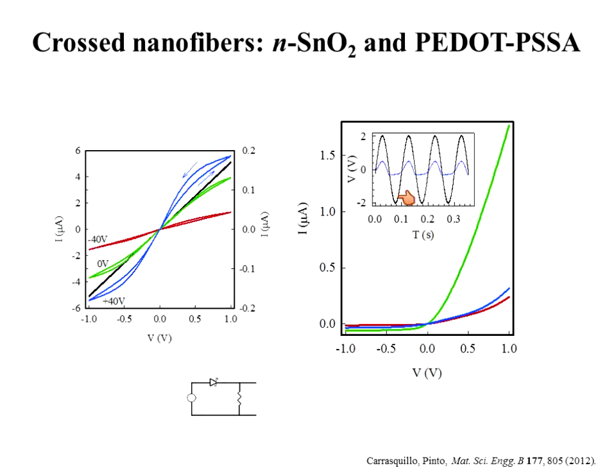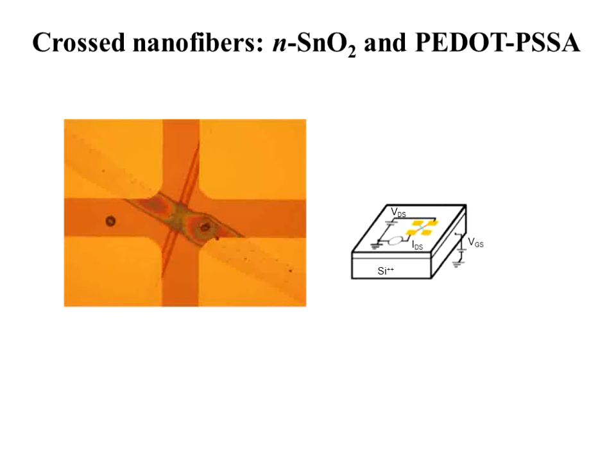But you see that the sine wave is applied at the entrance over here, and this voltage across the resistor would be this blue one. It's not a perfect half-wave rectifier, but it does show some waveform clipping. So a very simple device like this can show you waveform clipping, and showed you that one can use the electrospinning technique to make all of these devices in air, by the way. So this is all done in air. Puerto Rico is really very humid, and it doesn't seem to affect our devices. And as you can see, it's not very complicated to do this.